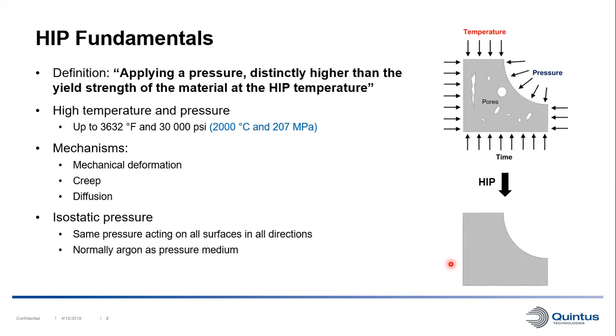But we don't only want to collapse the pores, we want to completely metallurgically heal these defects. And that is where creep and diffusion comes in to completely erase these defects from the microstructure. And since creep and diffusion are time-dependent processes, that's why we have a soak time in our hip cycle. Isostatic pressure is when you have the same pressure acting on all surfaces in all directions on an object. And for the hip process, this is normally achieved by a pressurized argon gas as pressure medium.